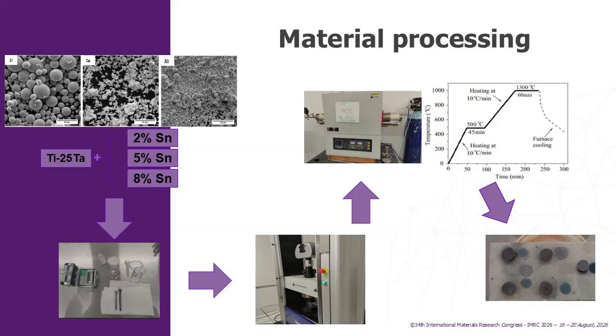The samples were manufactured using the powder metallurgy technique. The powders were then mixed, PVA was added as a binder, and they were compacted using a universal testing machine. The samples were extracted from the device to proceed with their sintering in a furnace.